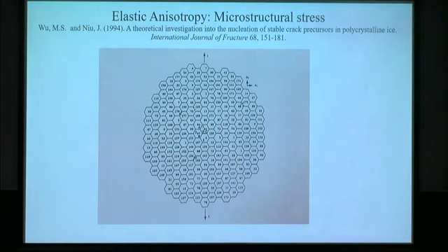Here, I'm just going to quickly go over some of these results. We consider something like 208 grains, I forget exactly. Just now in the illustration I isolated 4; you can isolate 4, 5, or 200 grains or whatever, and perform the SLP procedure. Now these numbers that you see within each grain refer to the C-axis orientation. This is 170 degrees, this is 90 degrees, 127, 270. So we use a random number generator to arbitrarily assign C-axis orientations for each of the 208 grains that we analyzed.